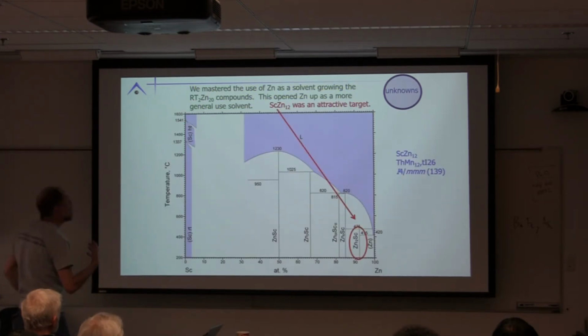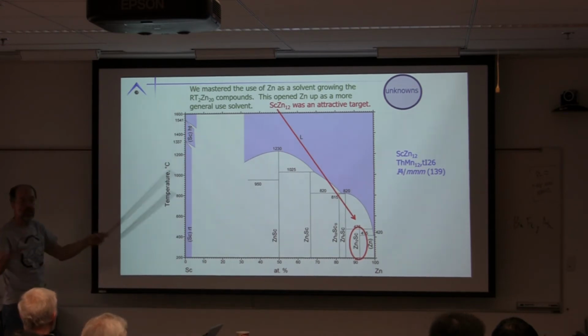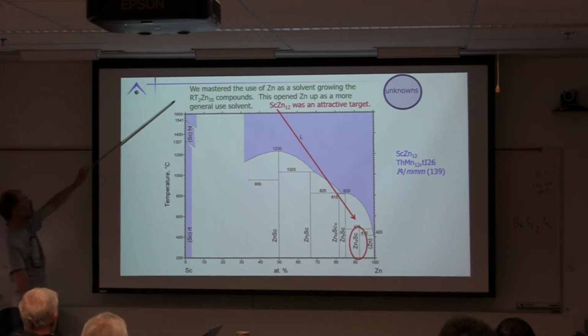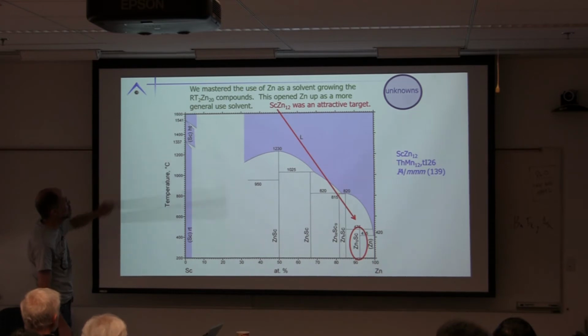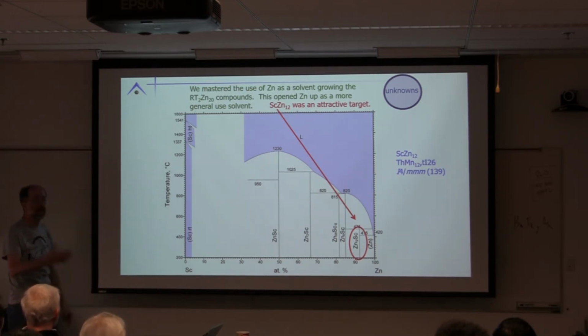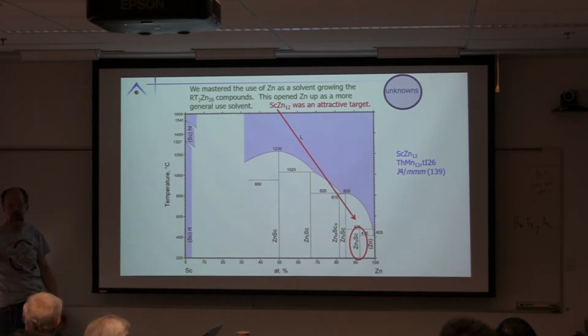Unknown unknowns. Okay? We mastered zinc as a flux. It's non-toxic, but it has a high vapor pressure. We did this when we were looking at rare earth transition metal 2 zinc 20 compounds. You can heat it up to about 1050. It doesn't blow up. If you heat it up to 1100, it blows up in silica. Okay, fine, so we know how to handle it.